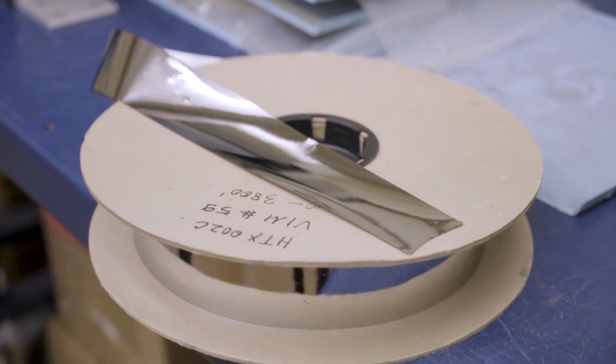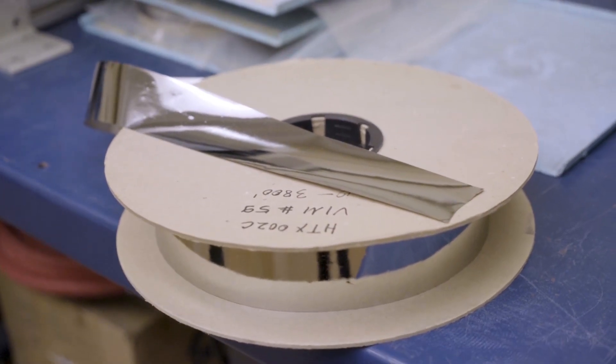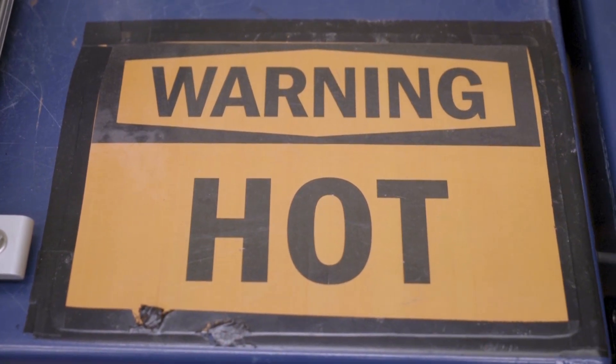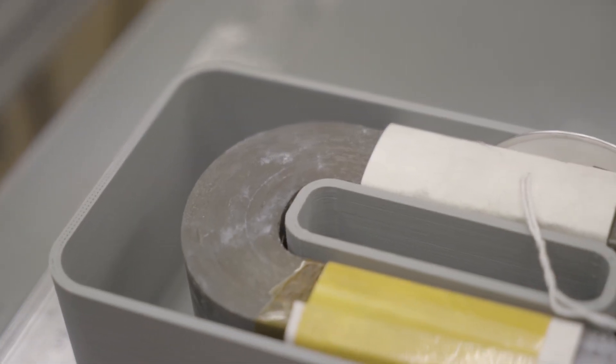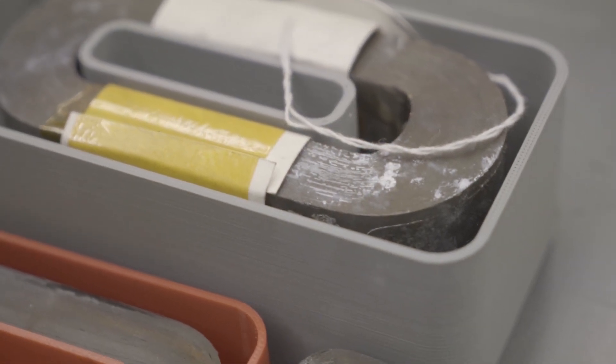If we do it in my laboratory here, we make small ribbons which look like this. They're 20 microns in thickness, so they're very thin — the heat is extracted very fast. These ribbons can then be wound up to form toroidal cores for power electronic components, and the small ribbons allow us to make small power electronic components for computers and electronics.